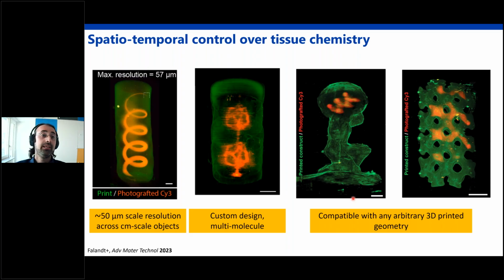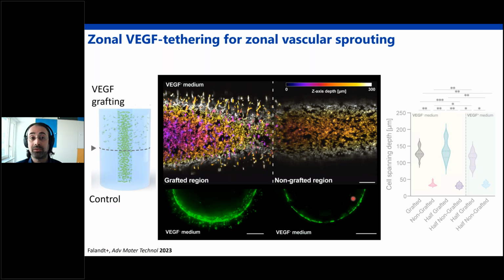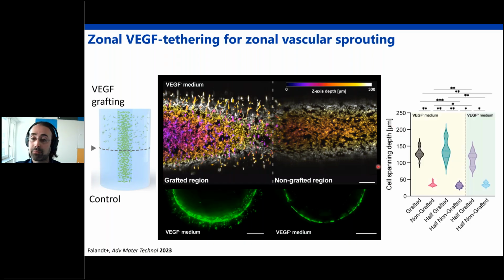In terms of functionality, we show this using vascular endothelial growth factor as a proof of concept. This is one of the key growth factors in blood vessel sprouting and angiogenesis. So we print some very simple channels, lay them down with the endothelial cells, and then graft VEGF on only one side of the construct. What we can see in these channels is that only the grafted region, regardless of the absence or presence of VEGF in the media, shows the endothelial cells sprouting and invading the gel, attracted by the gradient of this growth factor, something that doesn't happen in the region where the growth factor is not present. And of course, this can be quantified from imaging.